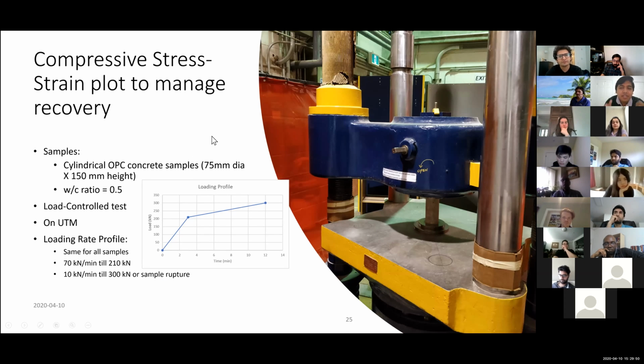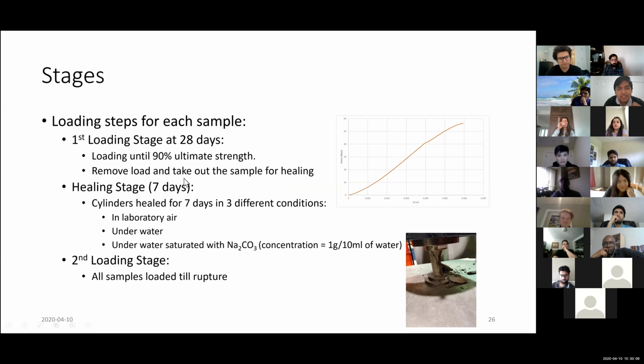So this was similar to the split tensile test that I did, and this is just compression instead of the split tensile test. Again, I did the same things. This is just the loading profile that I used in the Baldwin machine in the structures lab. I first tested for ultimate strength and then loaded all the samples up to 90% of their strength. Then I removed the load, took out the samples for healing, tested it on that day for damage, and then again after healing I compared those values. So this is roughly a similar test to the split tensile test, but just in compression.